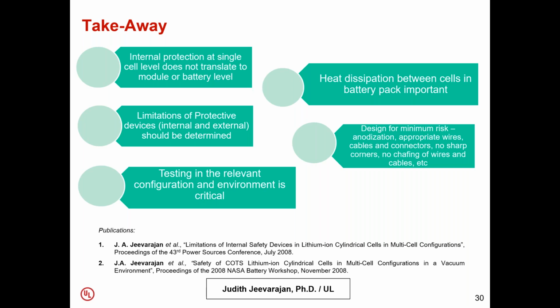And coming to the high impedance short circuits, one cannot put too many fuses. So it would be nice to have what we call a design for minimum risk, where you take care of all the different factors that can go into mitigating the risk of short circuits. You do the anodization, you size the wires, cables, and connectors appropriately. Make sure there are no sharp corners in your battery design, so there is no chafing of wires or cables. In that way, you can reduce the risk imposed by short circuits.